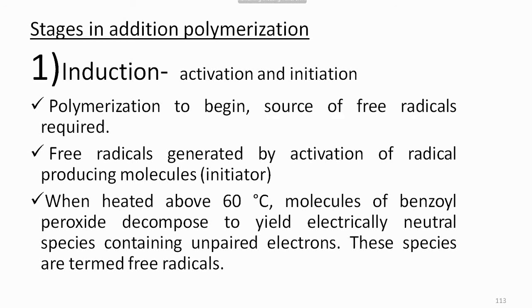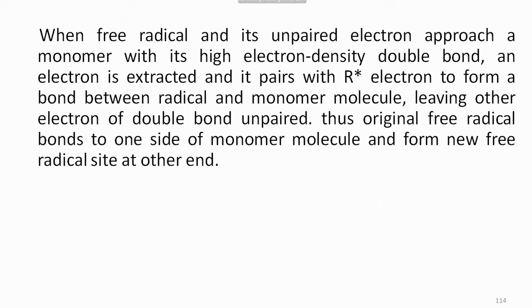So when we apply heat, how do we apply heat? We use boiling water, we heat the water, okay? Water in some special unit where the temperature is maintained around 60 degrees centigrade. Actually, it's 67 degrees centigrade. When there is enough heat, that is around 60 degrees centigrade, what happens is benzoyl peroxide decomposes, breaks down into two free radicals, and induction takes place.